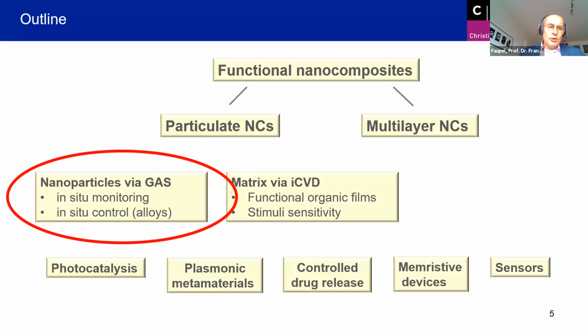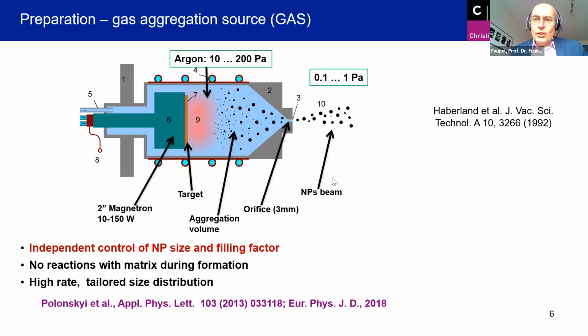So let me now say a few words about tailoring of such nanoparticles in these gas aggregation cluster sources. The principle is quite old. It was developed by Haberland already many years ago. And the idea is to have a normal magnetron, which you also use in magnetron sputtering, and then you sputter off atoms into the gas phase. And in order to form clusters, we have a high pressure of inert argon or other gases. And then due to the high gas pressure, we have many collision processes between the metallic particles and the gas atoms. And this allows nucleation of metal particles. And then we have an aperture here, an orifice, and the particles are deposited into an ultra-high vacuum on the sample.